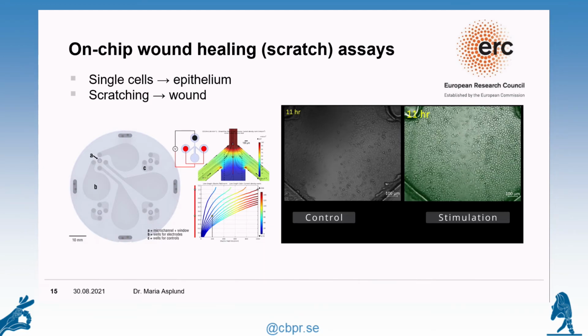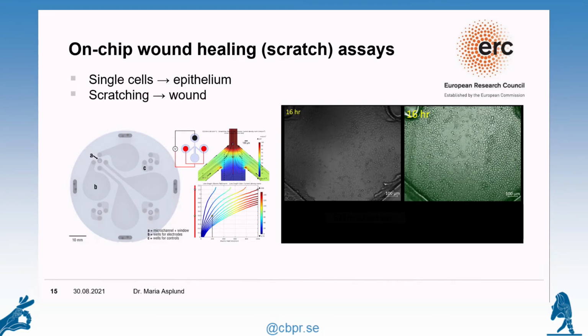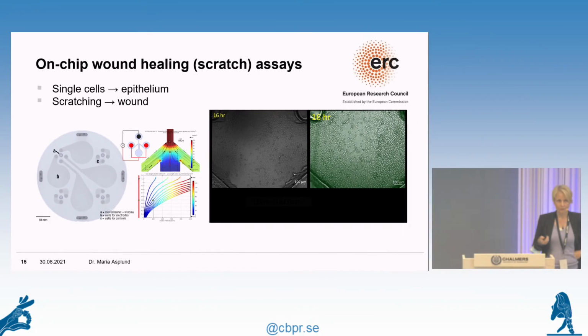And the reason why they come out looking fairly similar is because the field here is not fully directed towards the wound center, but actually it's a channel system where the field direction will be a little bit in the center and then up in this narrow channel here. So this is the reason why we don't see more of an effect, but it's really clear that the cells behave this way.